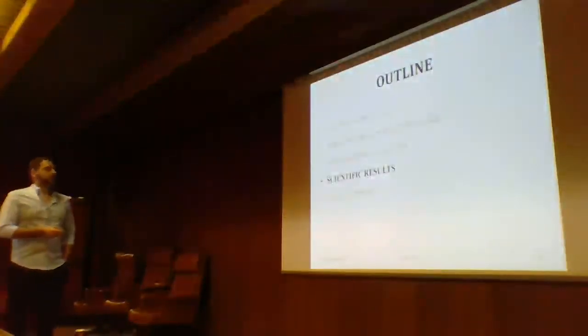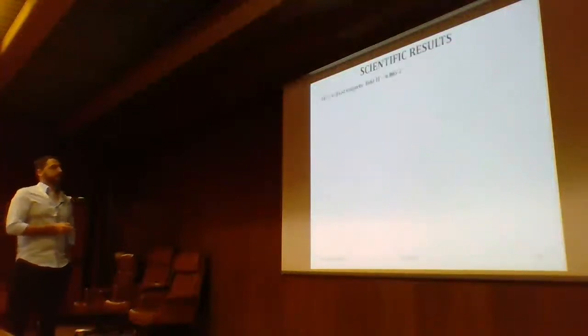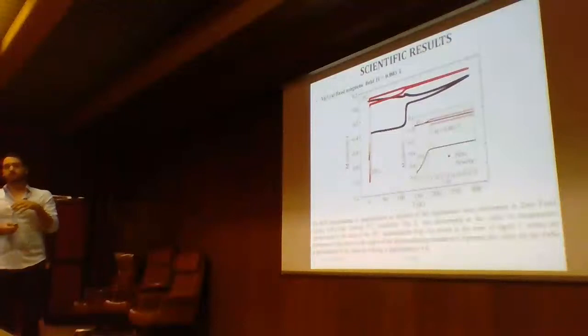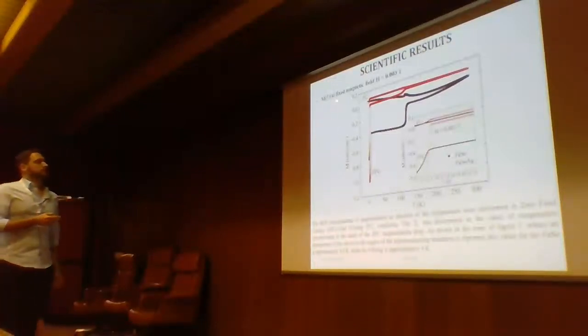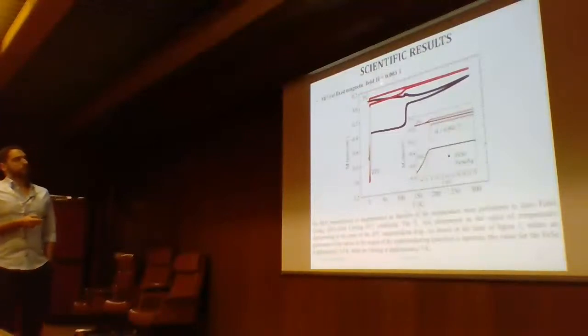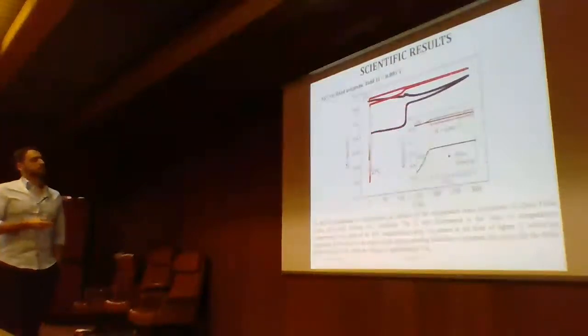Now, let's see the scientific results. In particular, we want to study the effect of the silver doping on our iron selenium sample. We can start with the magnetization as a function of temperature measurement, and this was performed at a fixed magnetic field of 30 Oe. In this picture, the black data are for the iron selenium, and the red ones are for the iron selenium with silver doping.